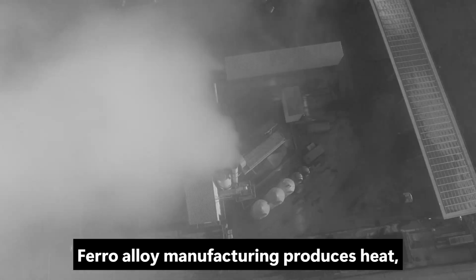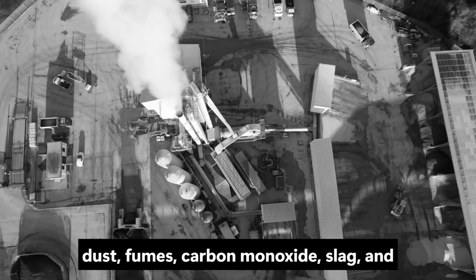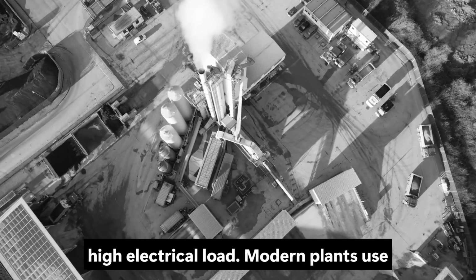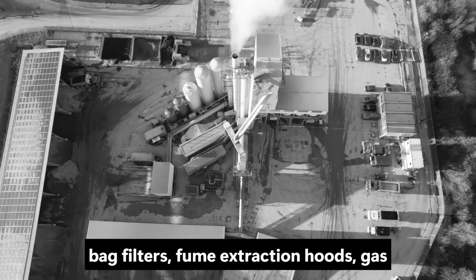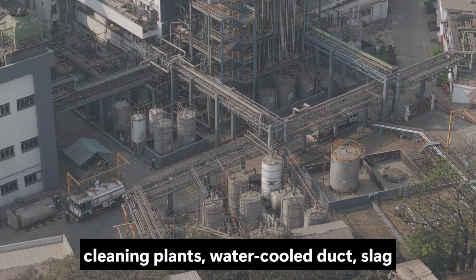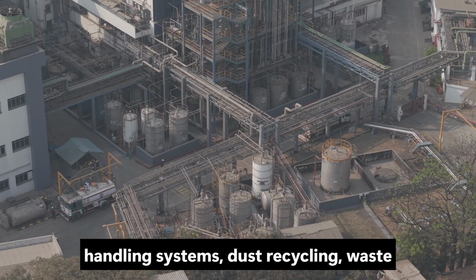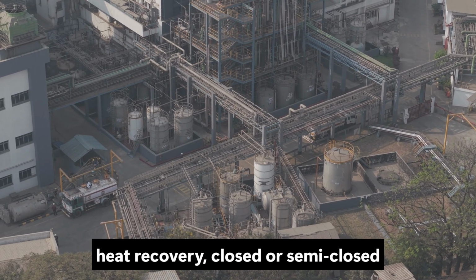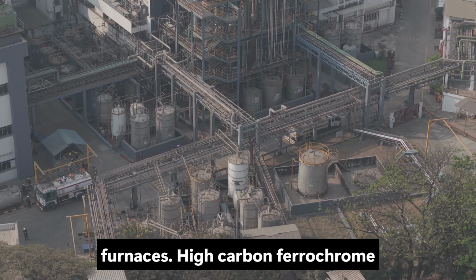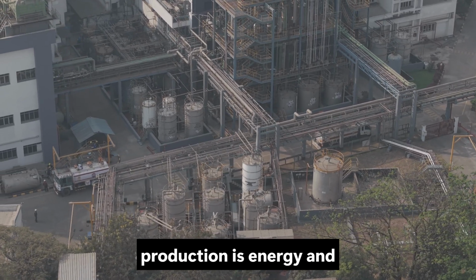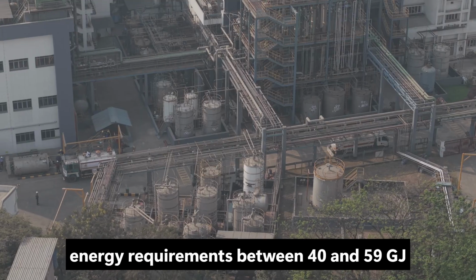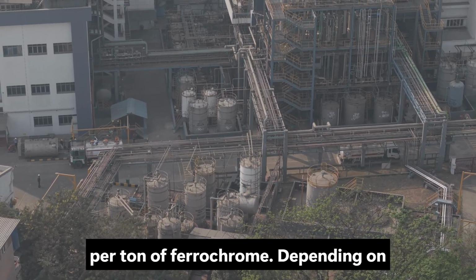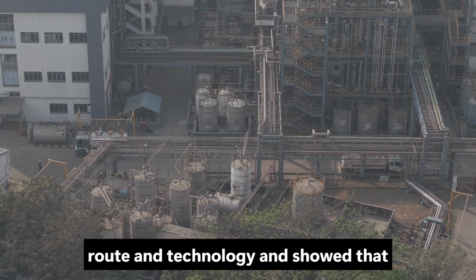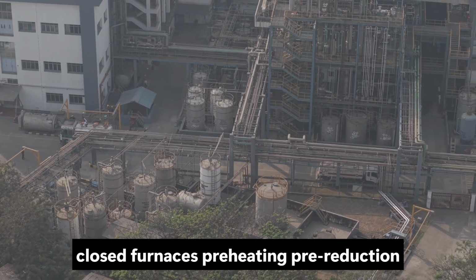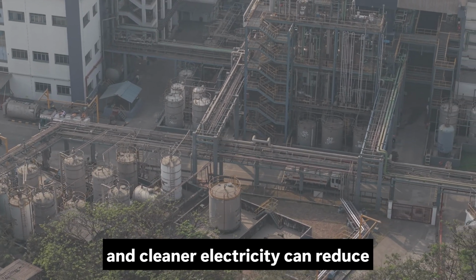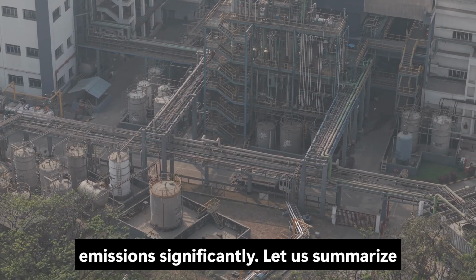Ferroalloy manufacturing produces heat, dust, fumes, carbon monoxide, slag, and high electrical load. Modern plants use several environmental control systems: bag filters, fume extraction hoods, gas cleaning plants, water-cooled ducts, slag handling systems, dust recycling, waste heat recovery, closed or semi-closed furnaces. High-carbon ferrochrome production is energy and emission-intensive. One study estimated energy requirements between 40 and 59 GJ per ton of ferrochrome, depending on route and technology, and showed that closed furnaces, preheating, pre-reduction, and cleaner electricity can reduce emissions significantly.